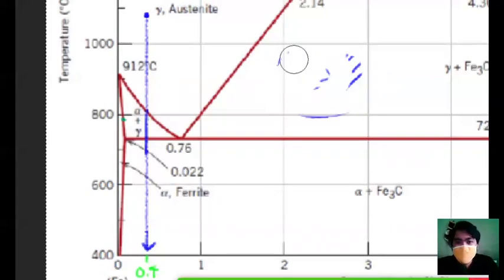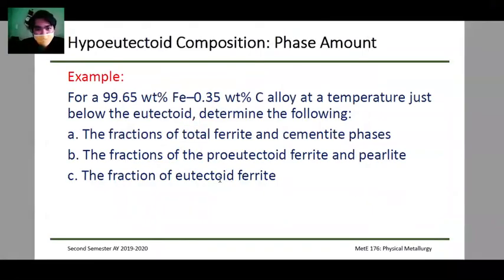So with that said, we can measure the pro-eutectoid alpha using the tie line and the inverse lever rule. So let's try, we have sample calculations here. For a 99.65 weight percent Fe steel system at a temperature just below the eutectoid, we are to determine the fractions of the total ferrite and cementite phase. Then we also measure the fractions of the pro-eutectoid ferrite and pearlite, and the fraction of the eutectoid ferrite.